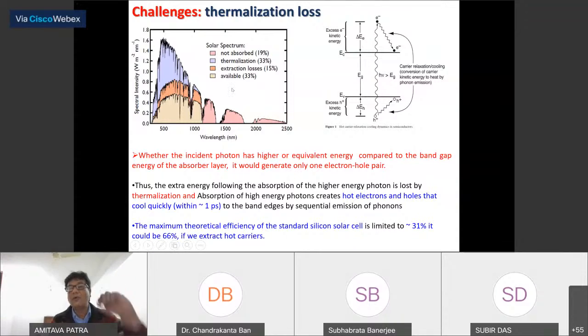Because in a semiconducting system there is a valence band and a conduction band. When light interacts with your system, the electron goes from the valence to the conduction band. But because the solar spectrum has different wavelengths, the electron can be excited from the valence to the conduction band, and gain excess kinetic energy. If you excite the system higher than the band gap of your material, then the electron goes to a higher excited state and relaxes to the conduction band. That is called the thermalization process, because this is a non-radiative process and that will heat up your system.